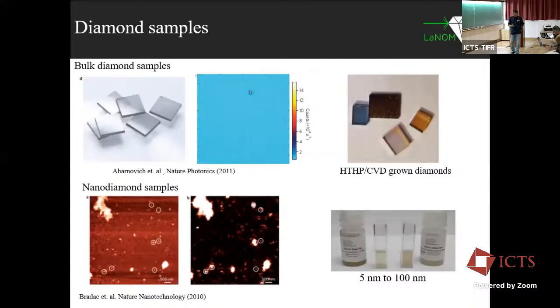When we talk about diamond samples, usually we get two types. This is for students, and we classify them in two categories. One is called bulk diamond samples, which are either CVD grown or HPHT, high pressure, high temperature grown samples. You get these pieces of glass in your hand. You do a typical confocal map, identify an emitter, and do all the spectroscopy or spin measurements there. And this is a real picture of some of the samples in our lab.